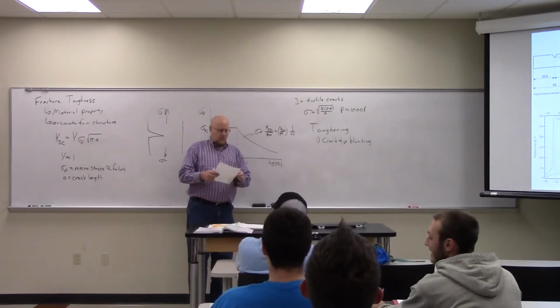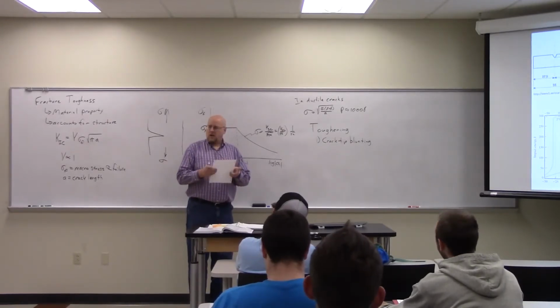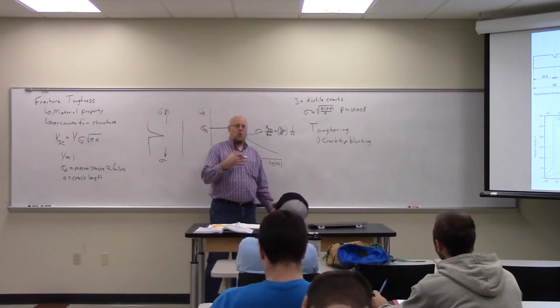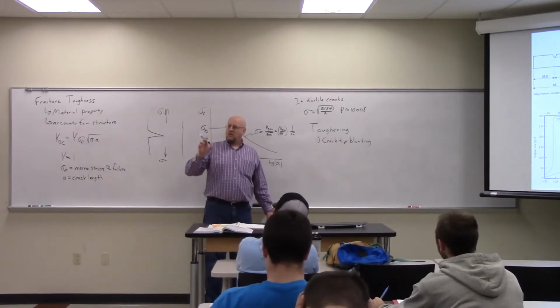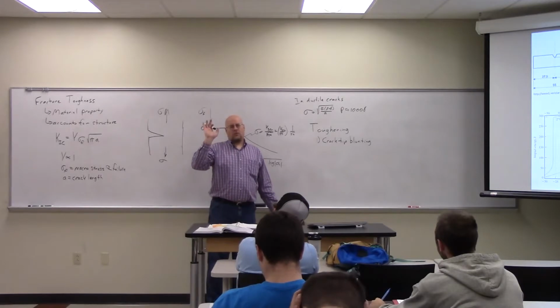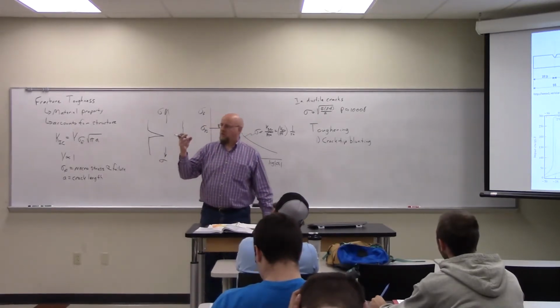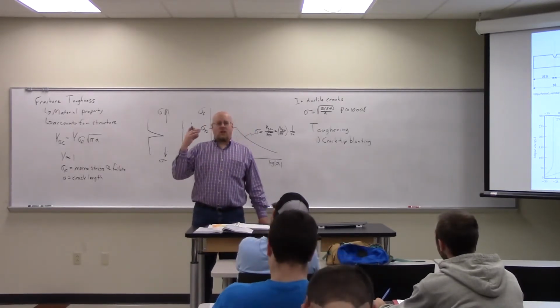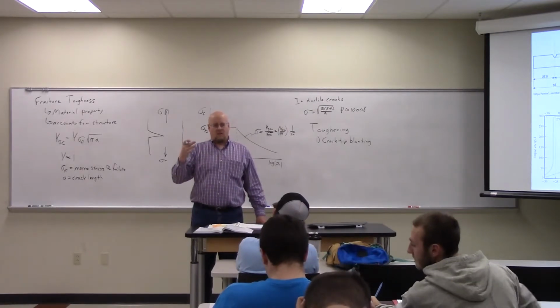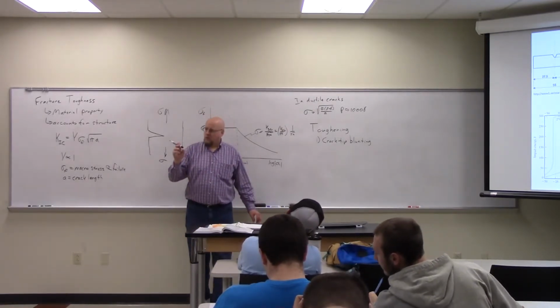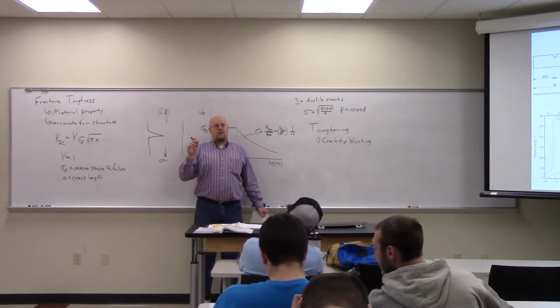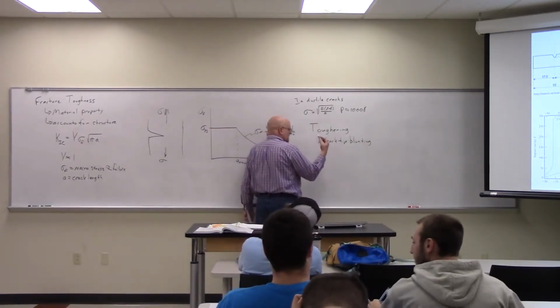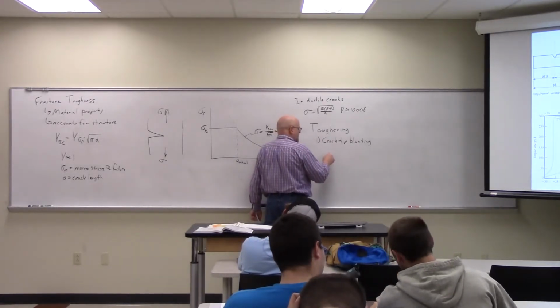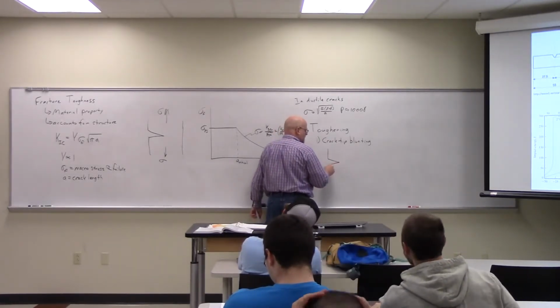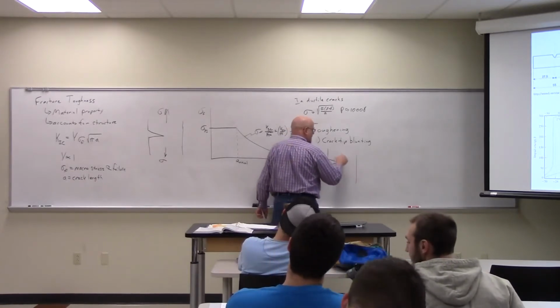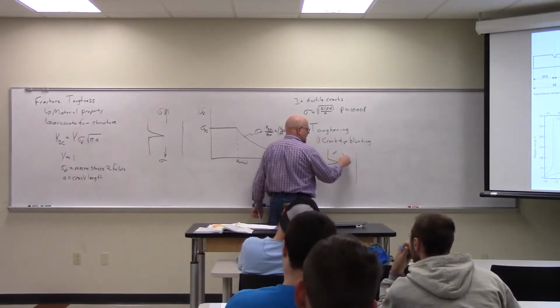There's a microcrack. Cast iron. Depending on how you make your cast iron, you can make it more or less tough by changing the shape of, because cast iron, we'll talk about this later, but cast iron actually has little bits of ceramic embedded in it. And you can actually change the behavior of the cast iron by changing the shape of those little ceramic bits that are embedded. Because if you have, like that picture there shows, cracks in the material, or yeah, little micro cracks in the material. They're kind of randomly oriented micro cracks.